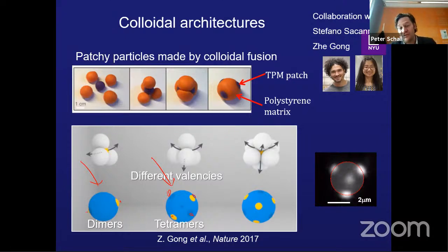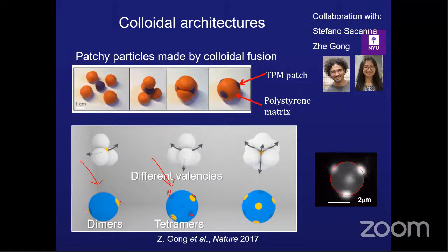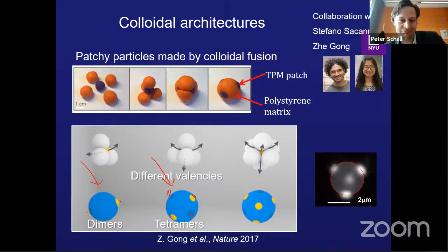So the result of that synthesis is that you have various different particles depending on your starting droplet. If you start with 3, as shown here, then you get this patch; if you have 4, you get these 4 patches, etc. So you get a whole mixture of these, and then you have to somehow separate them. Okay, thank you. Yeah, and the separation is tricky. You only get so pure. You do it by centrifugation many times.